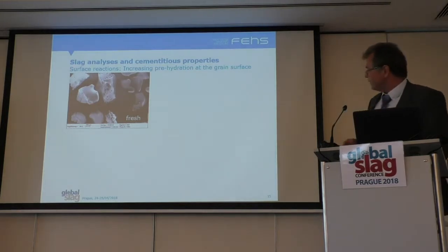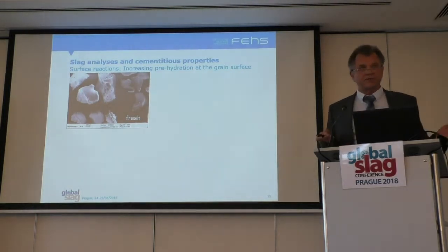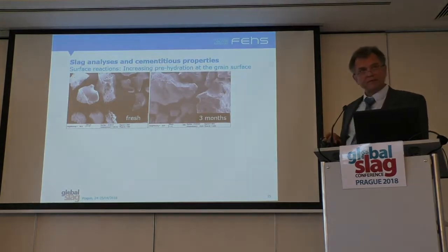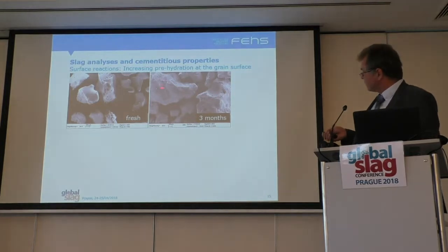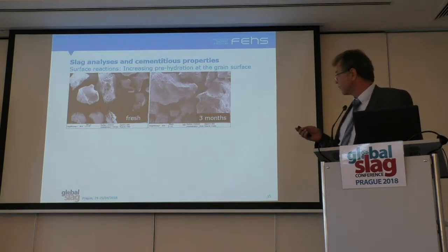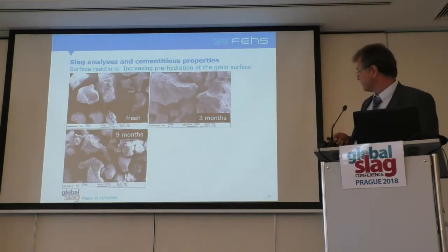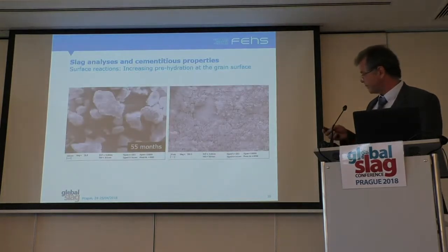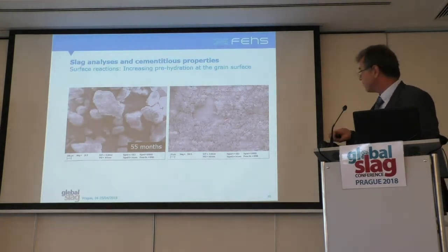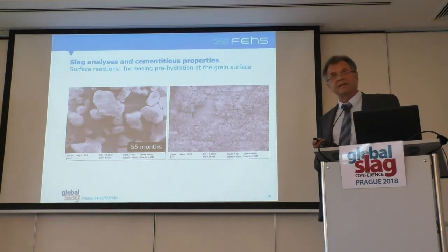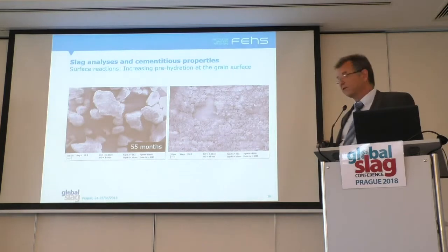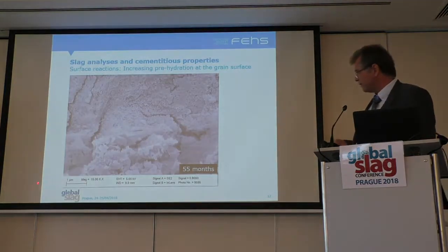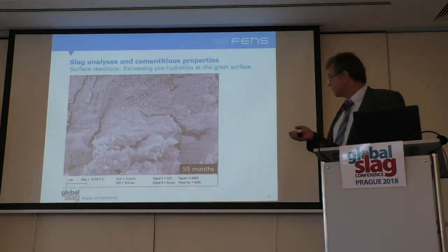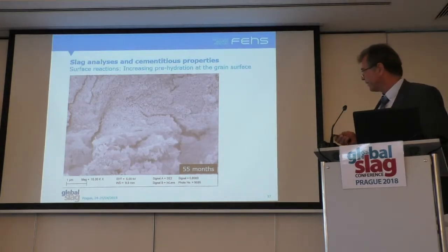Surface reactions. Let's look at the fresh GBS stored at Dillinger Hütte. Sharp edge particles, smooth surface, a certain amount of pores. Normal. After 3 months, you can see surface reaction products, not so dense, but you can recognize them. After 9 months, more and more. And after 55 months, you have a very dense layer of reaction products, very fine products at the surfaces, being responsible for the hardening of the slag. You can see it, that's a scale of 1 micron, so a lot of CSH phases in nanoscale, very dense.